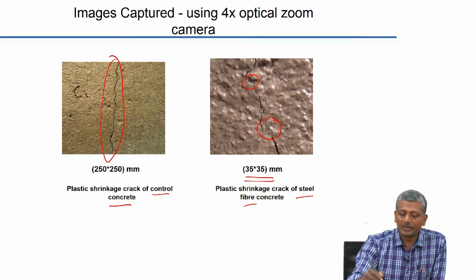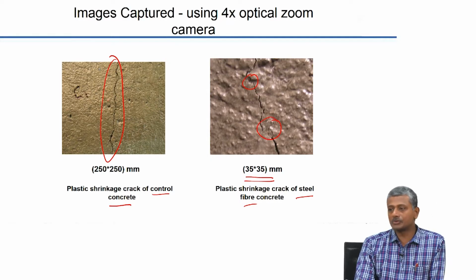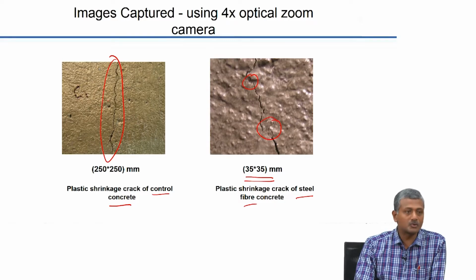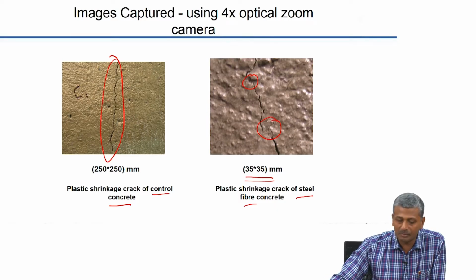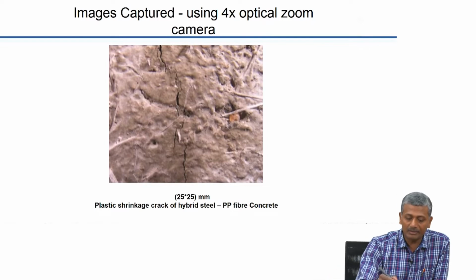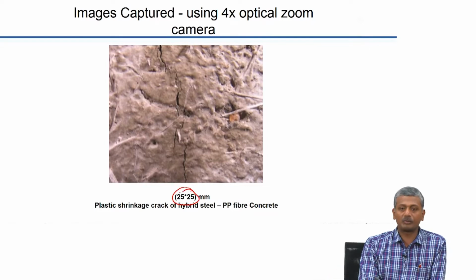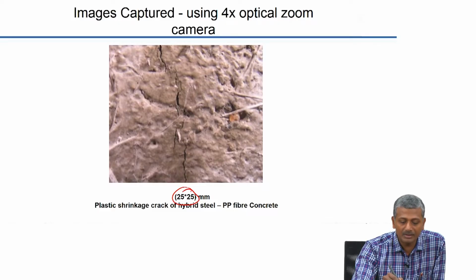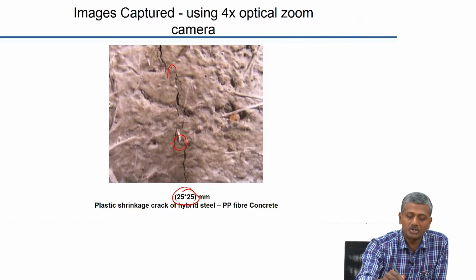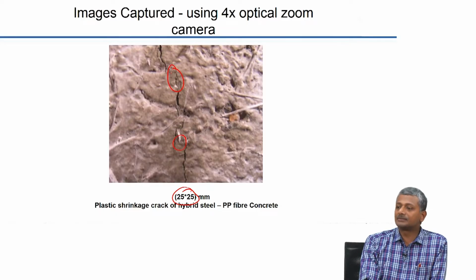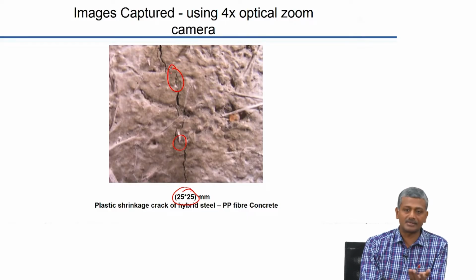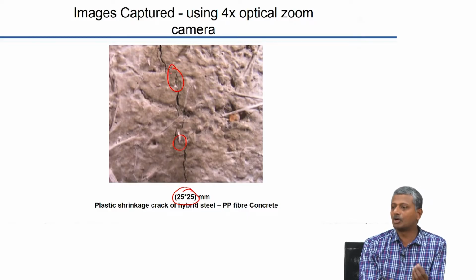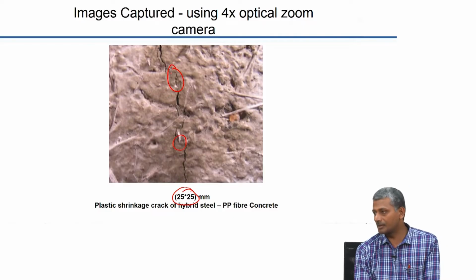Okay. So, the crack widths are obviously reduced when fibers are used, which we expect anyway, but what happens when we use a combination of steel and polypropylene? Is the performance better? And indeed, this is an even more magnified area, 25 by 25 millimeters, and you can see here the crack widths are even smaller than what we saw in the steel fiber case, and there is a lot more crack branching. Please remember that polypropylene fibers have much lower density than steel fibers. So, for a certain amount of fibers added in the system, you will have a larger number of fibers available.